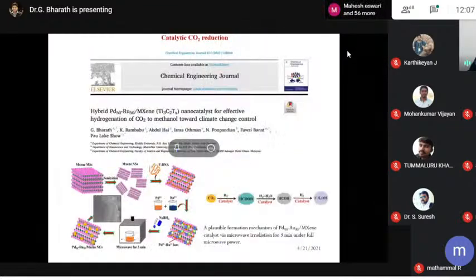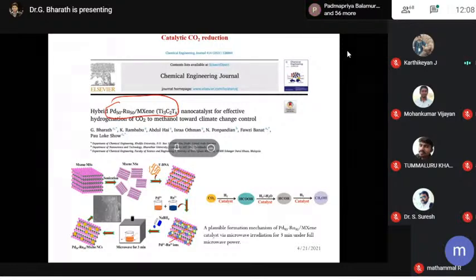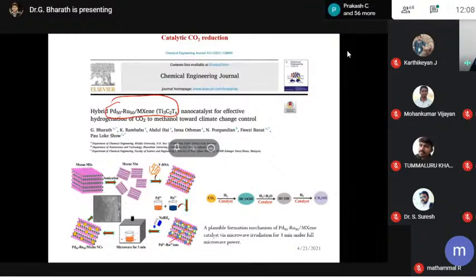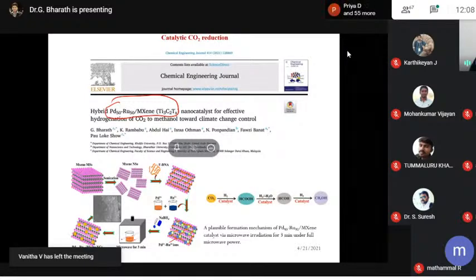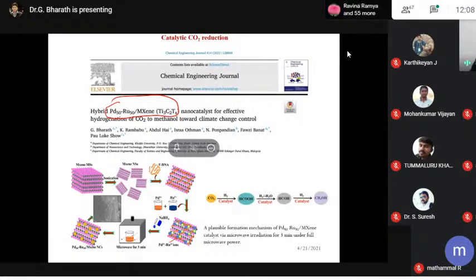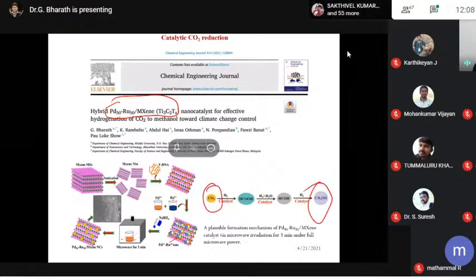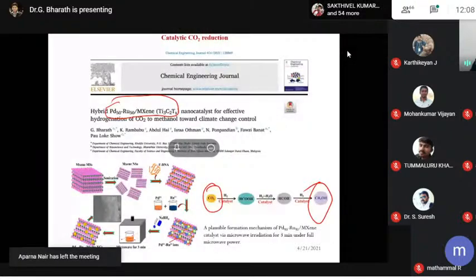This is one of our research articles, recently published. In this article, we used a hybrid palladium, ruthenium, and MXene nanocomposite. We know that MXene is a perfect acid-base substrate. This may help rearrange the carbon and oxygen bond also. And palladium and ruthenium are metal catalysts. These metal catalysts help to break the carbon and oxygen bond and then insert hydrogen. This is the main reason why we selected this material. With this material, we successfully converted CO2 into CH3OH. So this is the synthesis mechanism.